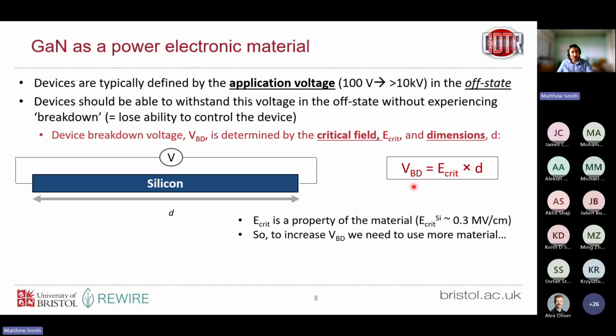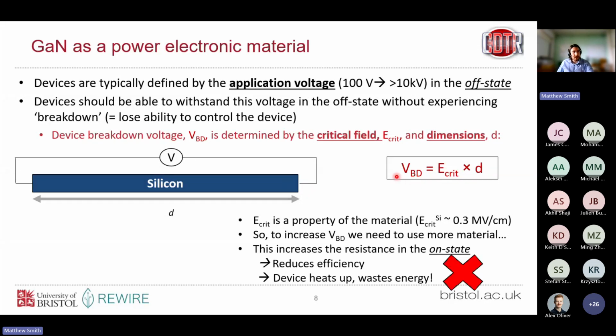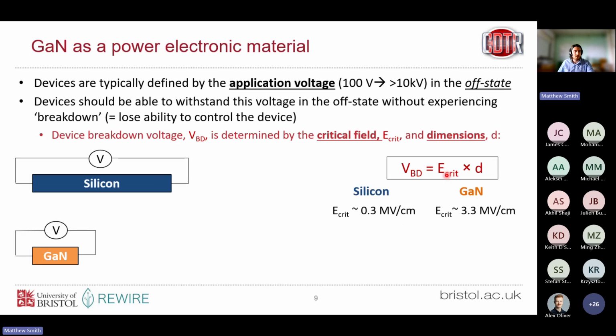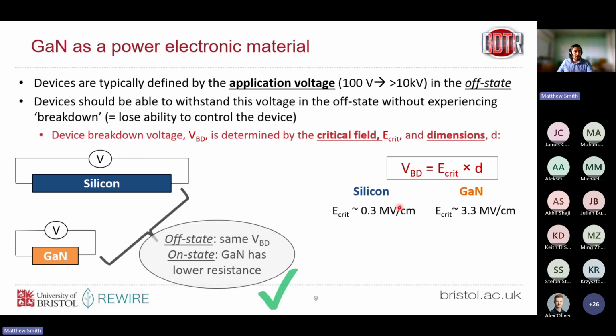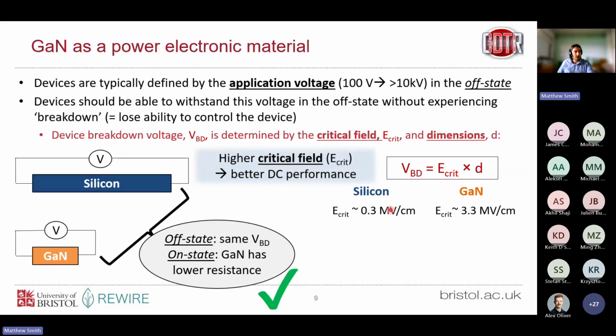That does increase our breakdown voltage, but it does so at the expense of efficiency. Now in the on state, our carriers have got further to travel, so our resistance is increased. So what we really want to do is look for materials with higher critical electric field. That's where gallium nitride comes in, for example, where we've got 10 times the critical electric field than we do in silicon. So that's the good news in the on-state and off-state trade-off. Critical electric field is advantageous.